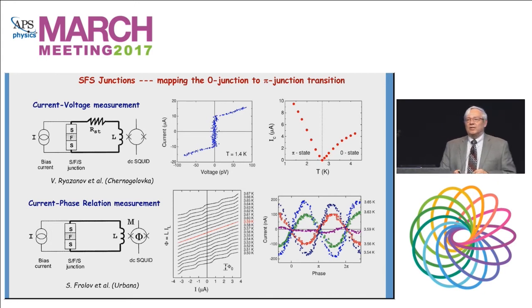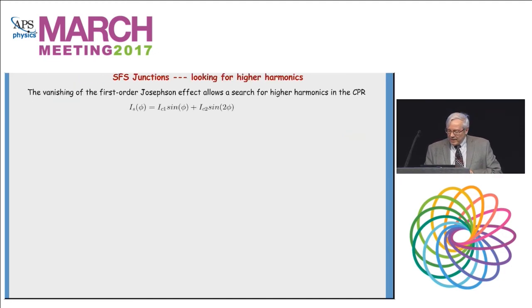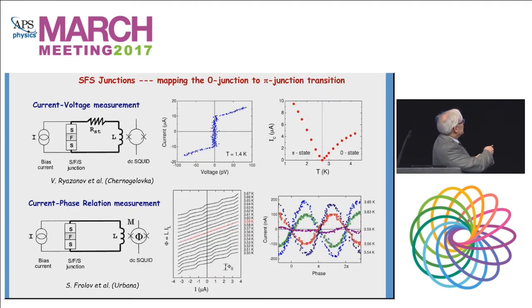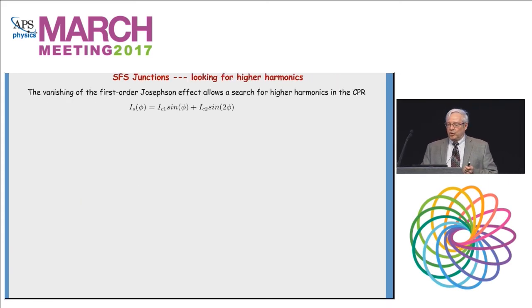So if you extract the current phase relation, you see it does indeed go from a sinusoidal current phase relation to no critical current at all to a negative critical current. So you can measure directly with the current phase relation this current phase relation pattern. Now, one nice thing about this, there is, of course, then a point where the critical current is 0. And when the critical current from the first order Josephson effect is 0, you're very sensitive to higher order terms.